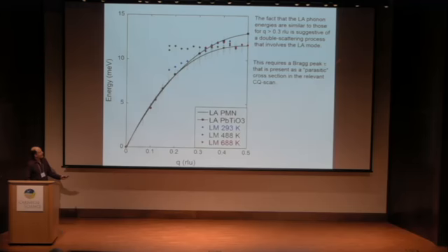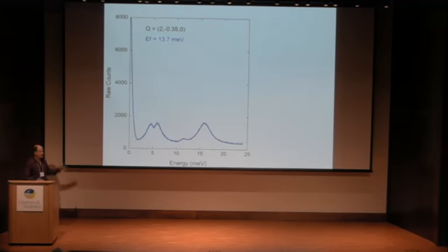Well, that requires a parasitic Bragg peak that is present and active during this relevant CQ scan, the constant Q scan that I've been showing you again and again and again. Okay, is that true? Well, here's that constant Q scan. I made it a little bit shorter. And we put a transmission scan on top of it, just like I showed you in my cartoon of the triple axis instrument. This is the 200 peak that takes a bite out of the acoustic mode. And looky here. We've got another parasitic Bragg peak process that's actually almost as strong. Note this curve goes up because the higher the neutron energy, the greater the transmission. So this is actually a large effect, and it's essentially right where the local mode lives.